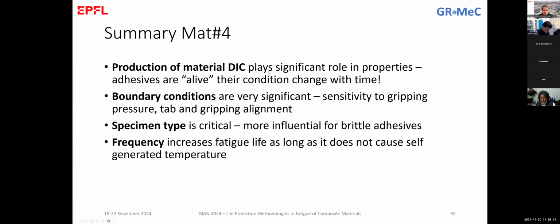So to summarize again, material number 4: we used DIC, which is again useful for giving significant information. The methods that are used for simulation are again valid, viable, S-N curves are valid for these specimens. And we have an understanding that for other specimens, the specimen type, the considerations from the standards have to be thought twice before followed, and we have to be very careful when we prepare the specimens. We've seen that the preparation of the specimen itself, the geometry, the alignment in the machine is very significant and can affect the results a lot.